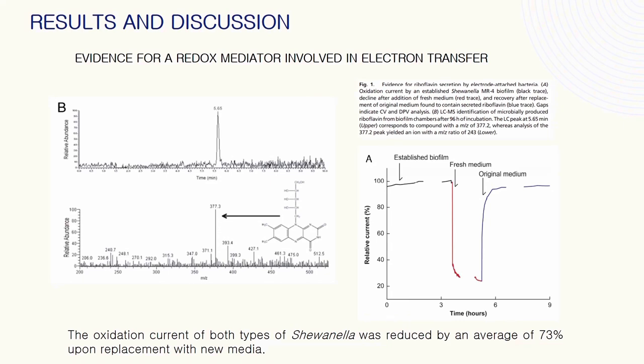In fresh media, no peaks were visible. In figure 1b, cell-free media from electrode-mounted cultures demonstrated maximum absorption at 450 nanometers and maximum fluorescence emission at 525 nanometers, consistent with flavin. Reverse phase liquid chromatography coupled with mass spectrometry detected a new constituent with a mass-to-charge ratio of 377.2 in the supernatant of a 96-hour biofilm, which is identical to protonated riboflavin.